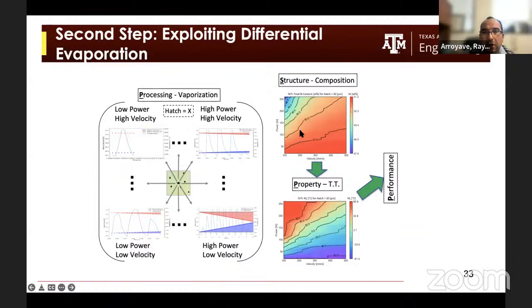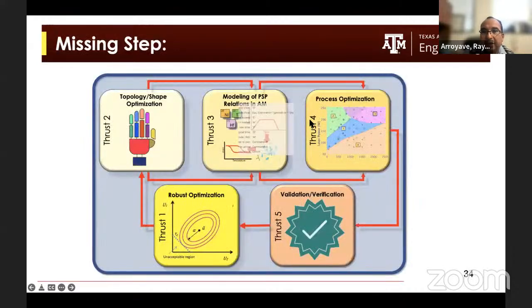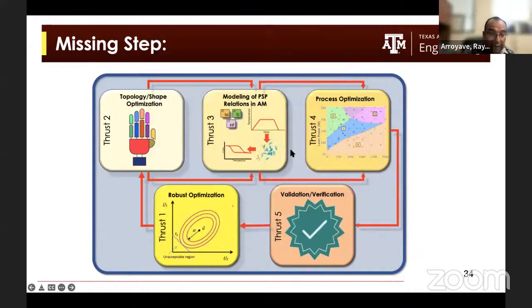After that, once we build this model, then we can build process maps that tell you how much the nickel content and the transformation temperature are going to change as a function of where you are in the power scan speed space, okay? The idea is, once we have this forward model, to start thinking about how we invert these forward models to start doing closed loop, objective-based algorithmic design for 4D printing, okay?